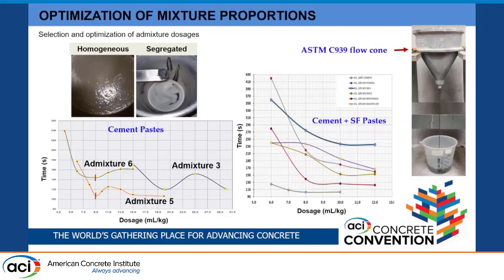One of the first steps that we make is to evaluate the compatibility between cement and the superplasticizers. The graphic on the left is the result for the cement pastes. And the graphic on the right is the pastes with cement and silica fume. You can see that the bottom graphic is for the admixture that results more compatible with the mixture with cement and silica fume. As you can see, the variation is very important in the development of these materials, to make this test to define which admixture is the one that gives the best performance with that specific cement or that specific binder.